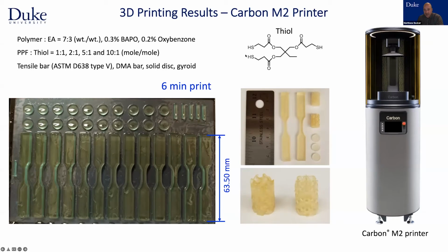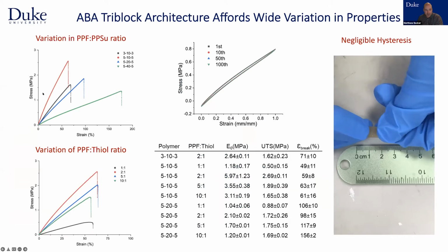But this is a fast thiolene-based printing that works up to 70% solids. And when you cross-link this, the ratio at which you cross-link it determines the rate at which it degrades. And if anyone's interested, I've got information at the end that you can dive into. And so the nice thing about it is that unlike many materials, there's no yield point. So this is a common stress strain curve that shows you a variation in the length of the cross-linkable units versus the lengths that aren't available or that span the cross-linking units. And you can see that can be tuned widely. Also, if you vary the cross-linking ratio, you can determine the rate that this degrades.